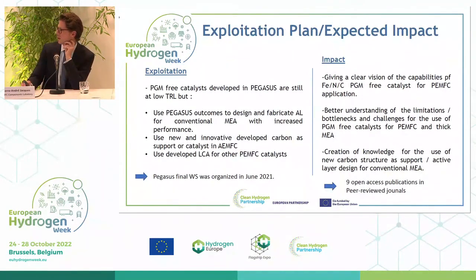Then, exploitation of our project. The catalysts that have been developed are still at a very low TRL, so we cannot make exploitation of that product. That makes no sense. However, in that project, we could make recommendations to formulate and to design the active layer structure for the cathode side of the MEA. We can also use this material, iron, nitrogen doped carbon, as a new support for conventional catalyst.